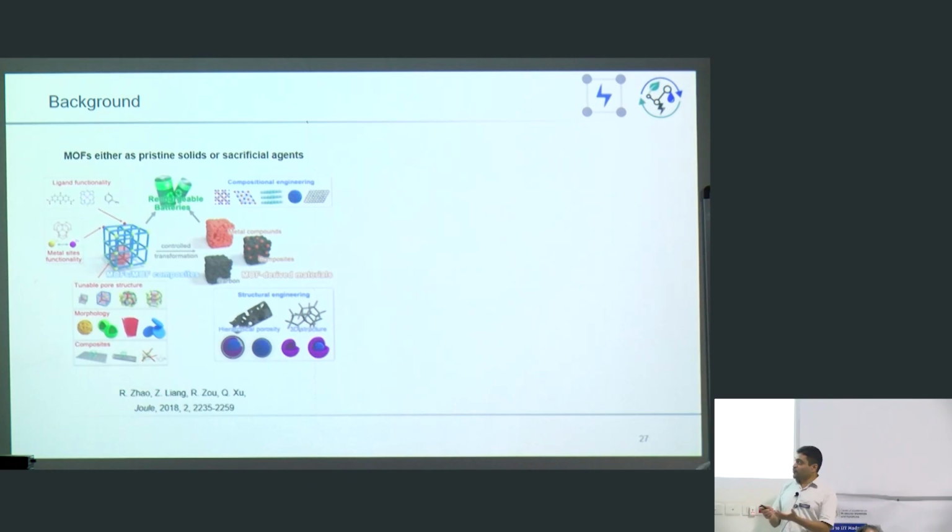The reason for it is the electronic conductivity is much lower. And the electronic conductivity is lower because the moment you have got porosity, all the functional groups are now apart from each other. So there is very little contact for the electron to hop or travel. So you're going to struggle to get good electronic conductivity with highly porous systems, right? So the more popular choice is you just make a MOF, burn it, and obtain carbon out of it. The carbon might have metal nanoparticles inside it, and you use this for supercapacitors, for batteries, and other things. So this is the more popular route.